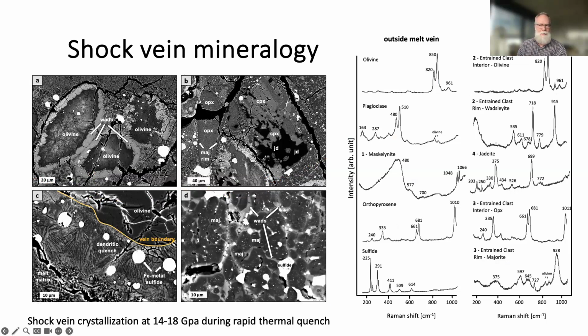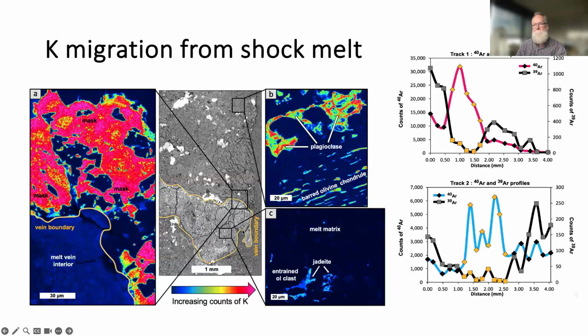So this is actually a reaction that involved exchange of iron and magnesium. We see very fine-grained dendritic quench at the edge of the vein, getting coarser toward the middle, and so on. And then this is what the melt vein assemblage is. It's majorite garnet plus wadsleyite, very similar to what we saw in the other sample of Mbale. And then these are just the Raman spectra of all the high-pressure minerals, demonstrating that we properly identified them.